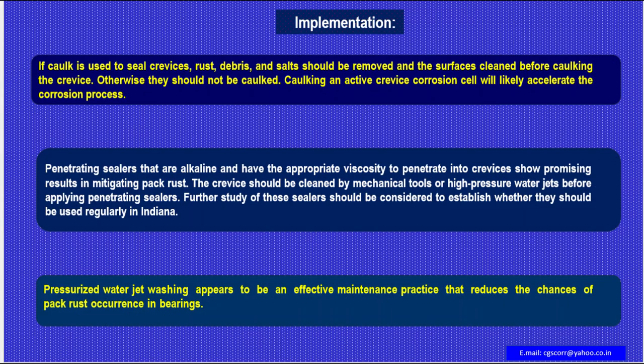If caulk is used to seal crevices, rust, debris, and salts should be removed and the surface cleaned before caulking the crevice. Otherwise, they should not be caulked. Caulking an active crevice corrosion cell will likely accelerate the corrosion process. Penetrating sealers that are alkaline and have the appropriate viscosity to penetrate into crevices show promising results in mitigating pack rust.